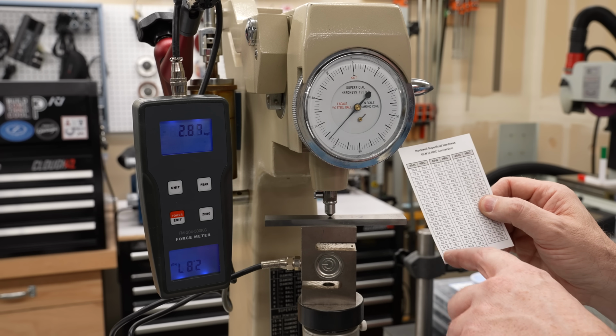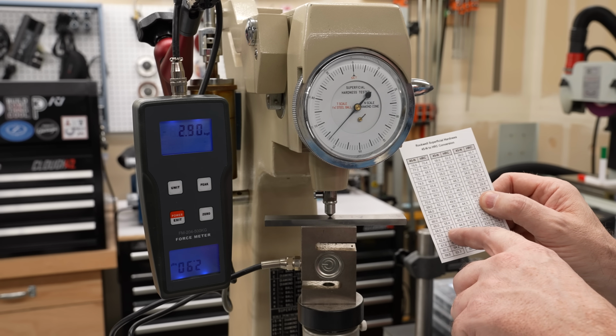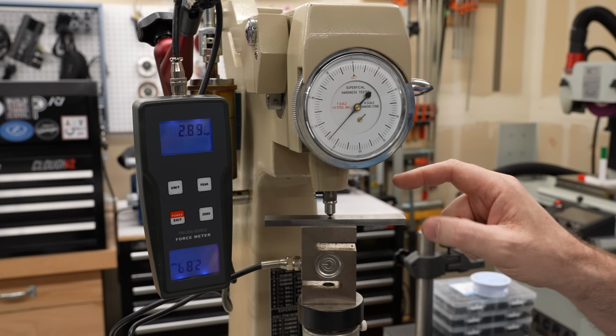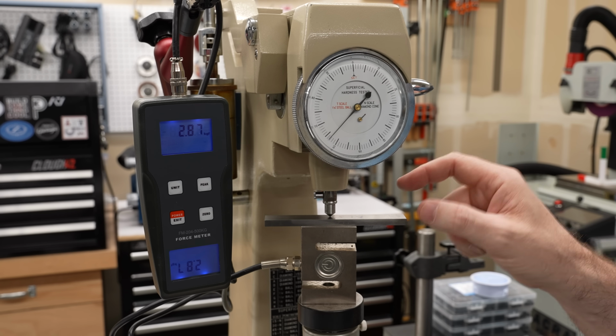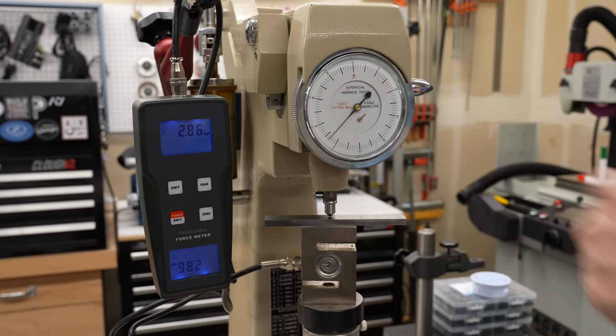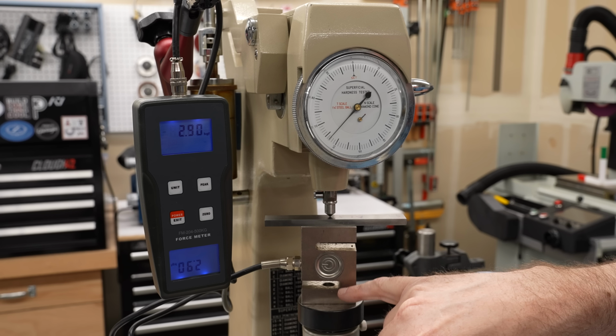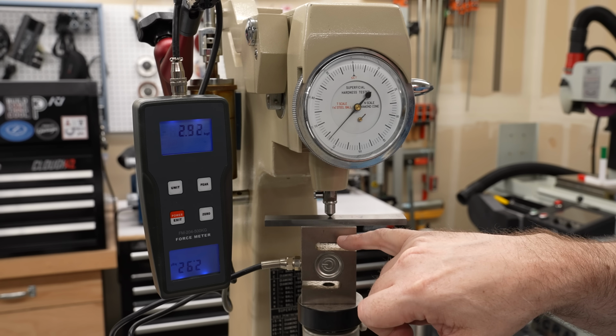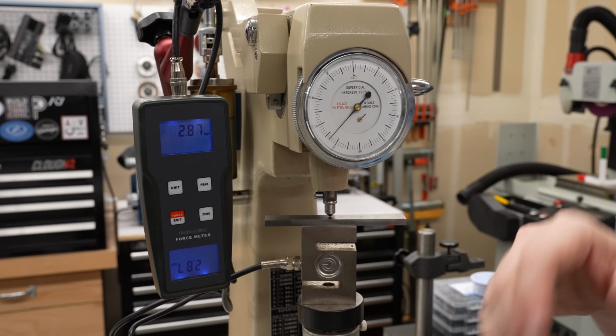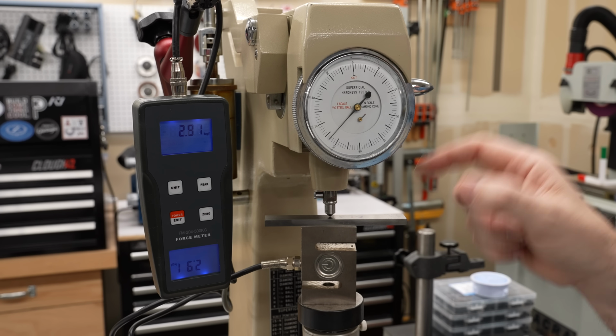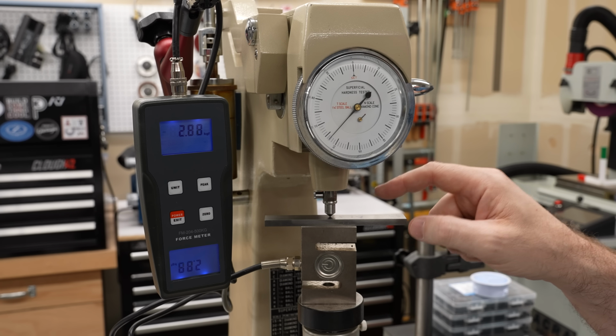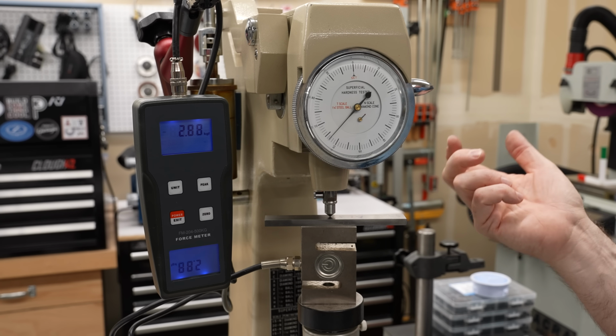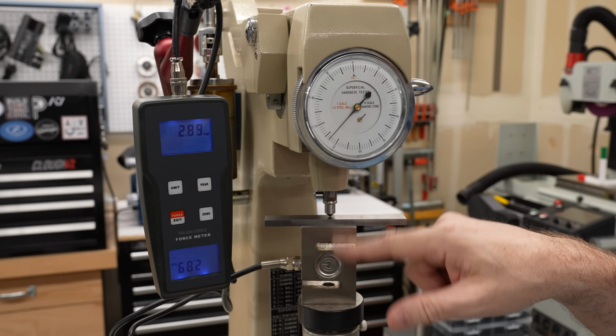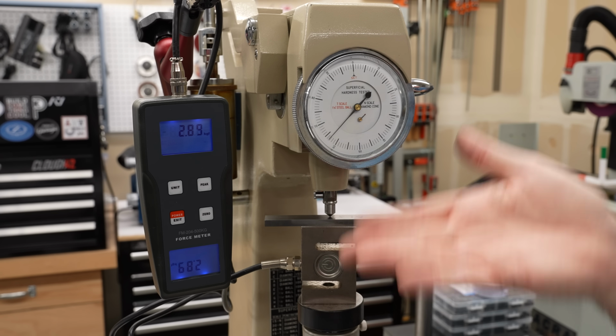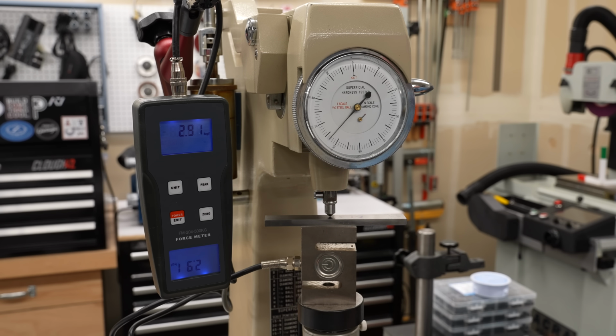If I look at my chart, 64 is 57.9 Rockwell C, and this is hardened and tempered A2 tool steel, so that sounds like we are in the ballpark. So even though there's extra flex here in the transducer, it doesn't really affect the measurement because we are initially loading it to 3 kilos, adding the test load, then pulling it back, so whatever flex is in here in 3 kilos gets canceled out in the reading, which is pretty neat.